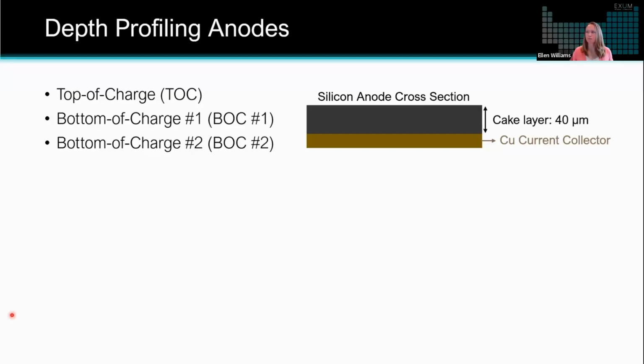and chemistry. So what we did in this study was 3 anode samples, one of which was extracted at the top of charge, 2 of which were extracted at the bottom of charge. The only difference between these 2 bottom of charge samples is where they were taken from the cell. One was taken from the center of the cell, the other one was taken from the edge of the cell. And so you can see this diagram here of each of the 3 anode samples.